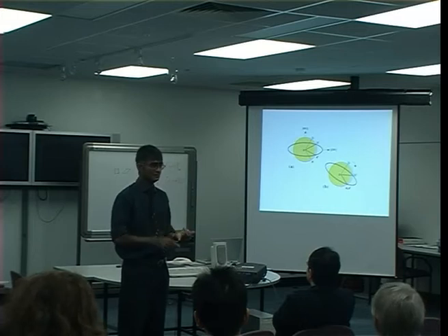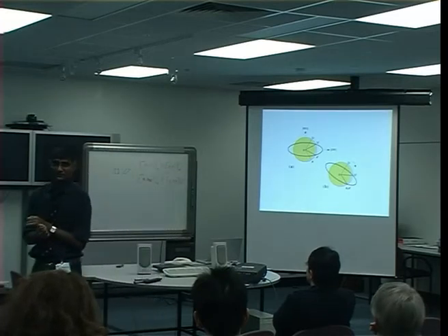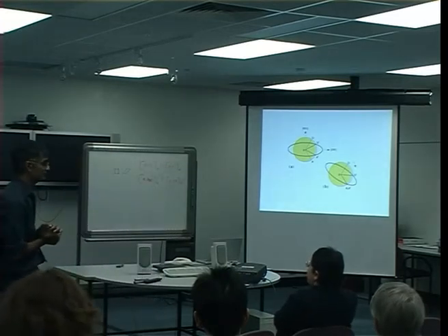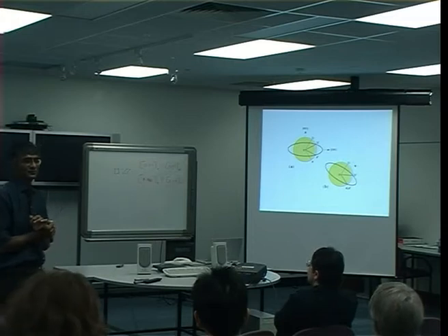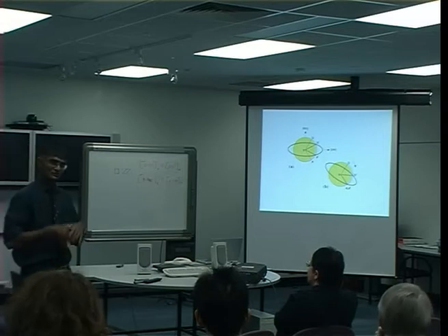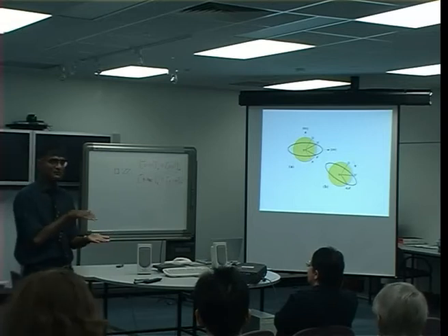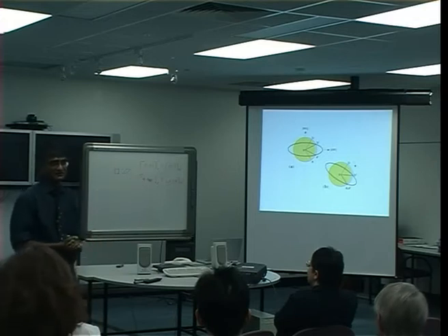So we can't satisfy the fundamental condition we came up with this morning, that the deformation which carries austenite into ferrite must leave one line coherent. Okay. So we are getting even more confused now. The deformation which converts the lattices is not only inconsistent with the shape deformation, which is an invariant plane strain, but it doesn't even leave a single line.